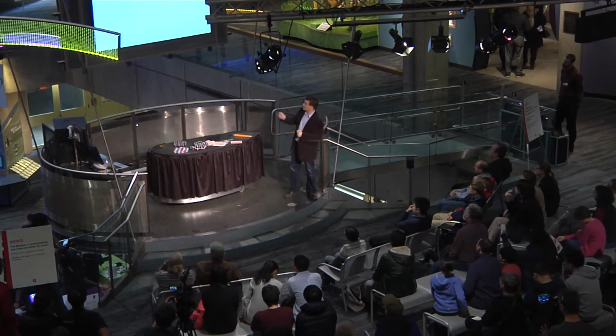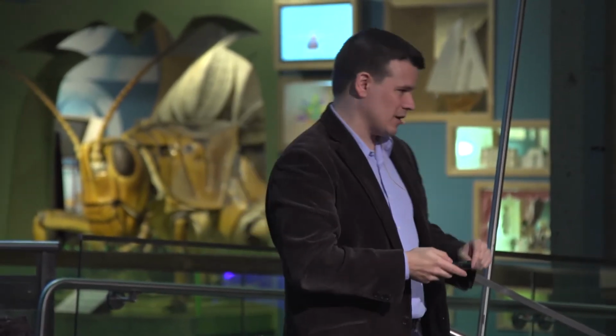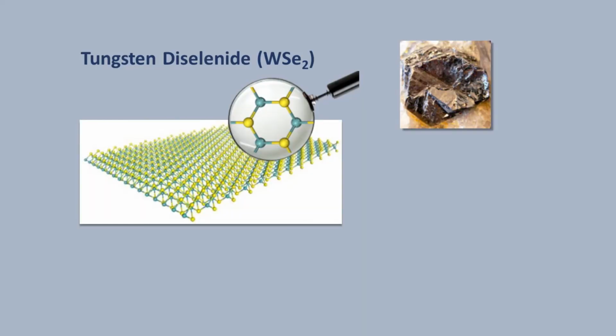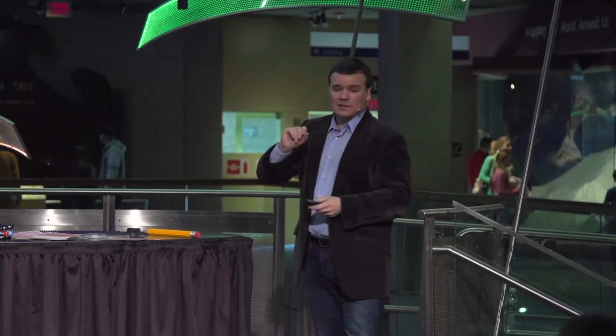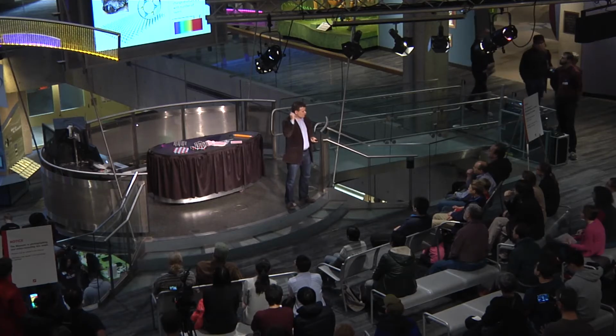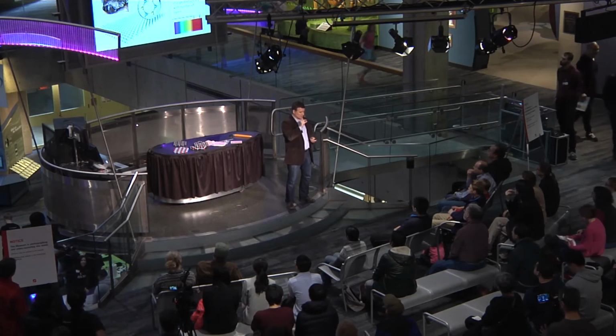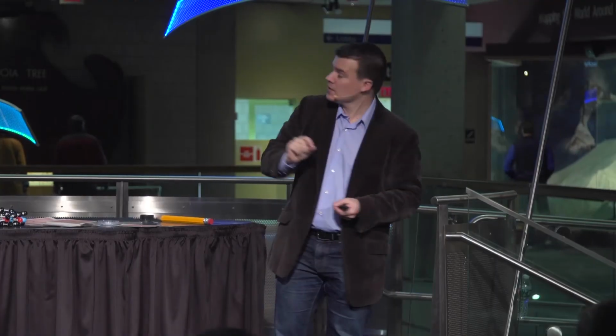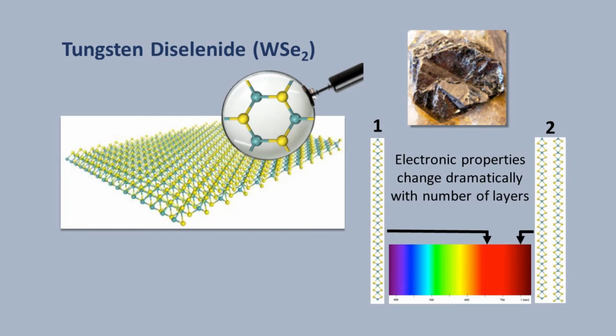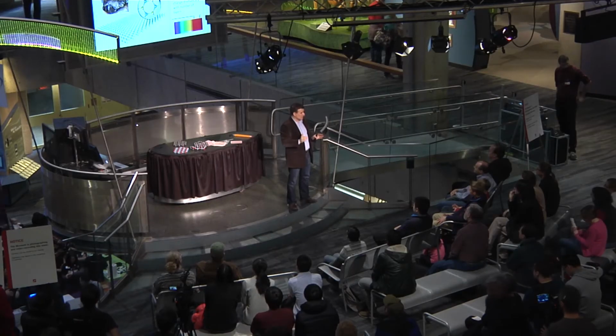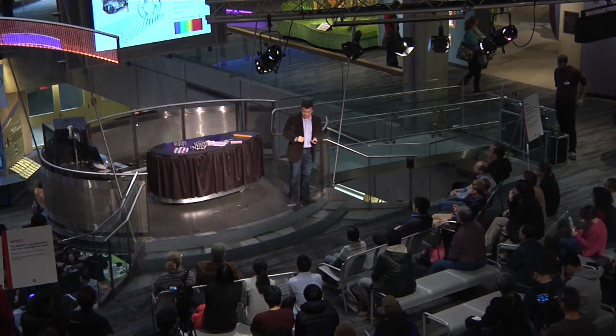For example, this material, tungsten diselenide. This material is not 1 atom thick, it's 3 atoms thick. One monolayer, 1 unit cell, we say, is 3 atoms thick. From the top, it looks a little bit like graphene, or like hexagonal boron nitride. And this material is a semiconductor, which, as you know, are very important for technology, for transistors and for computers. In fact, this material is fascinating because its behavior depends on the number of layers. For example, if you have only 1 layer, like shown here, it emits red light. If you have 2 layers, it emits infrared light. So the behavior depends on the number of layers. And that is a characteristic which is very common among these 2D materials. The behavior changes with the number of layers.